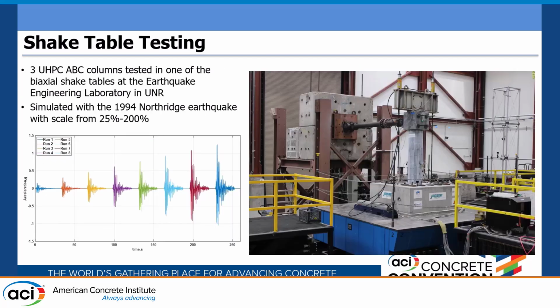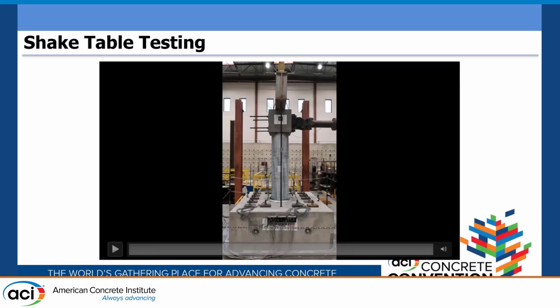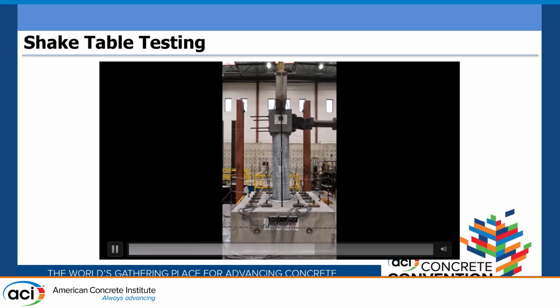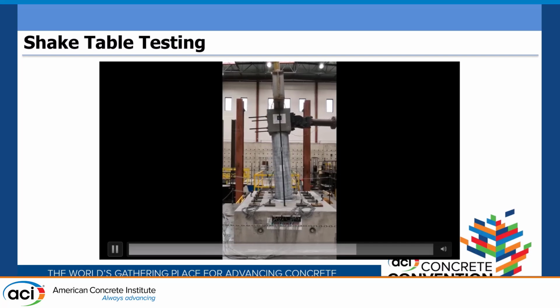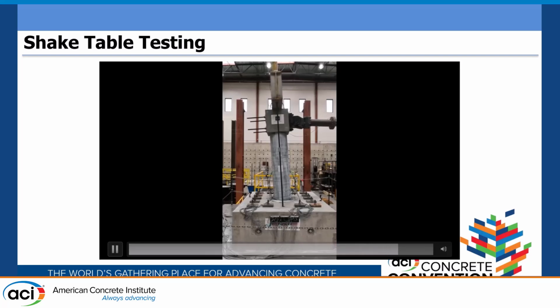We also wanted to try the dynamic part using our shake table. We did 3 columns under shake table testing, and we simulated the 1994 Northridge earthquake from 25 to 200%. We didn't reach 200%, we only reached around 175% until we broke it. So this is the video of what we did with the shake table. This is 150%. It didn't fail at this one. You're going to see a little bit of a cliff, where we failed after in 175%. So this is 175, and the column failed, rupturing the reinforcement.